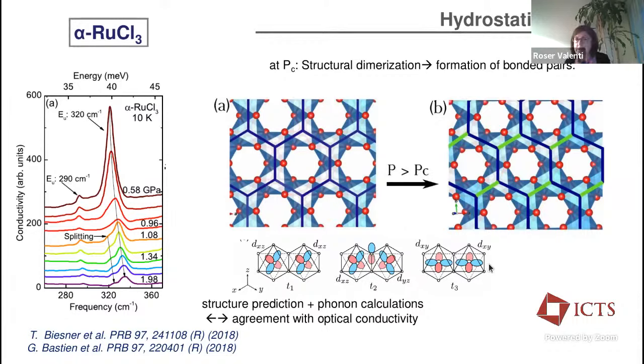So, at some critical pressure, what is happening is that you have bonding and antibonding, and the system in fact distorts. There is a structural transition to a distorted phase where you form these short bonds. There is a distortion, and what happens then is you have spin singlets, so magnetism is gone. And this distortion is observed here, for instance, in the conductivity by following this phonon that you find at about 1 gigapascal, where there is a splitting of this phonon corresponding to this distortion.